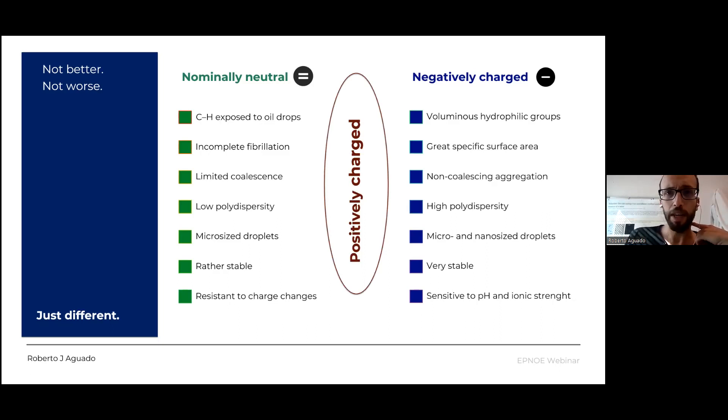So while we will probably have micro-sized droplets in the case of nominally neutral nanofibers, we will have a mixture of nanometric and micrometric droplets in the case of anionic nanocellulose stabilized emulsions. They will be, due to the charge and the high zeta potential, very stable in time, even more than those with neutral nanocellulose which are already quite stable. And of course, we are talking about things that can be protonated, deprotonated, all of that. So anionic nanofibers will always be sensitive to ions, including the hydrogen ion. And this may be counterintuitive, but cationic nanofibers won't stay like negatively charged but opposed. They will sit somewhere in between.